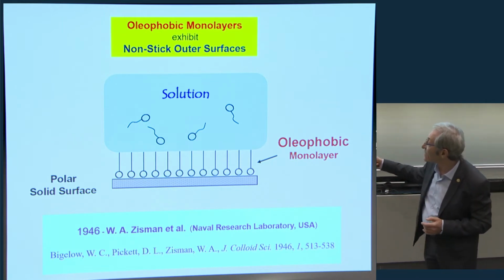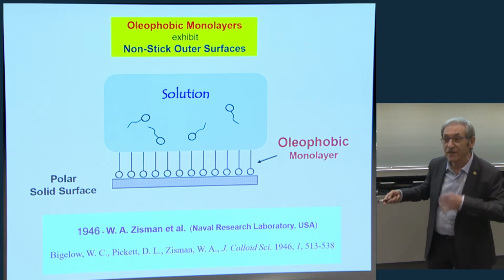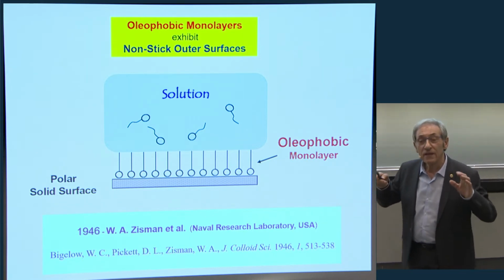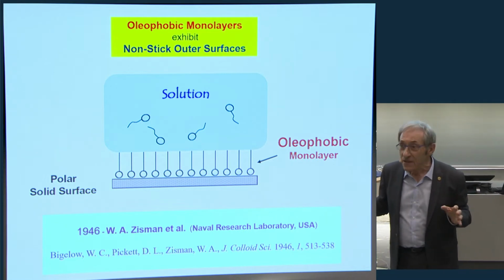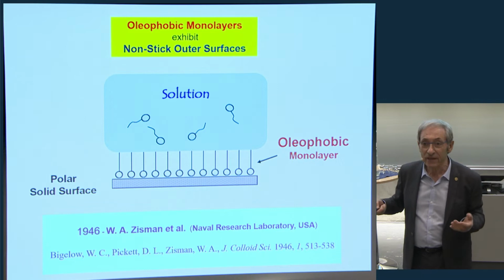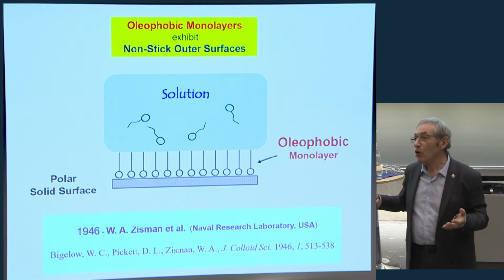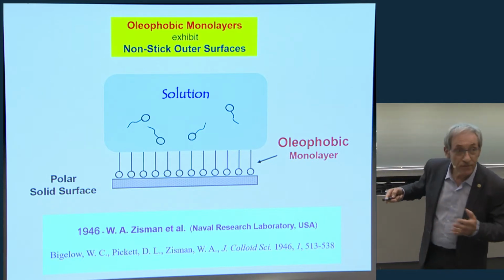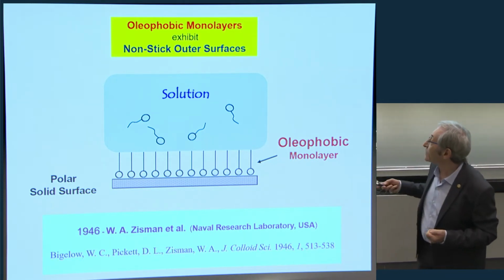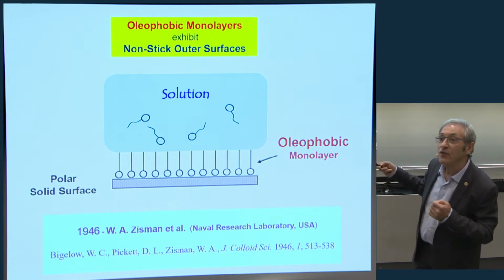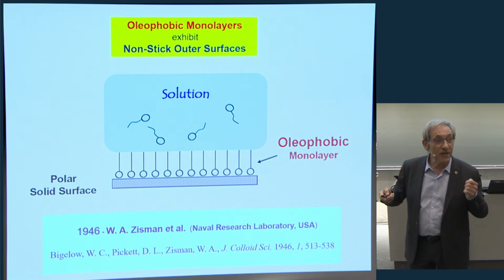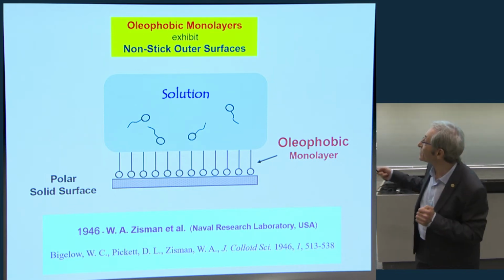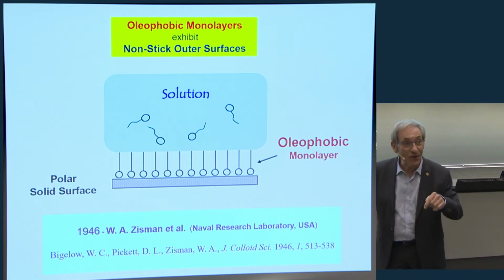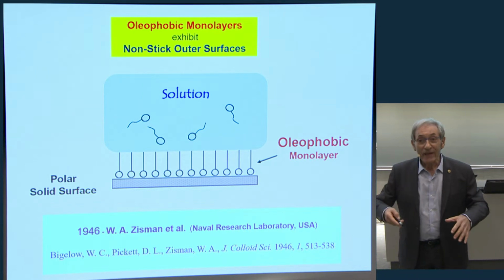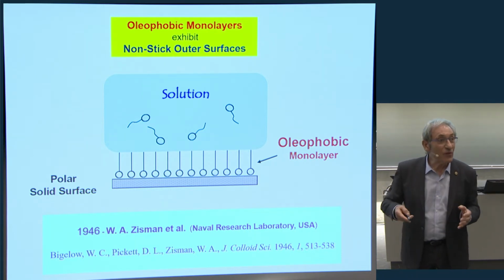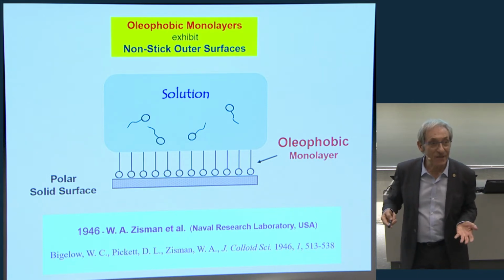The research that has been done, starting with this work, the first work was this one, in the 50s and also in the 60s, was focused on wetting properties, a lot of work on wetting, and on lubrication, and on friction. This is lubrication, of course. And by the way, this is the mechanism of lubrication in engines. You have in engines an oil, but the lubrication is not by the oil. The lubrication is by the monolayer that forms from molecules that are in the oil on the metal parts. So while there is wearing during metal parts moving one on top of the other, the monolayer reforms itself by self-assembly.